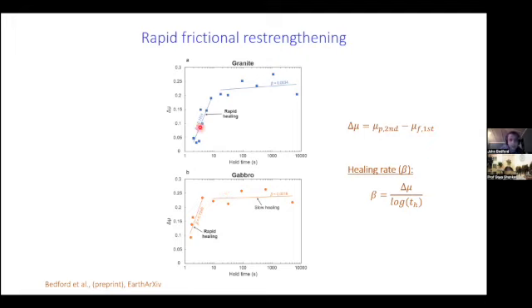And then after this initial rapid increase in frictional strength, the healing rate decays, and it actually decays to a value that is similar to what is observed in low velocity slide-hold-slide experiments performed at micron per second slip rates. And I've included some low velocity data just for reference here, and you can see the healing rates are of a similar order of magnitude after this initial rapid healing that we observe here.